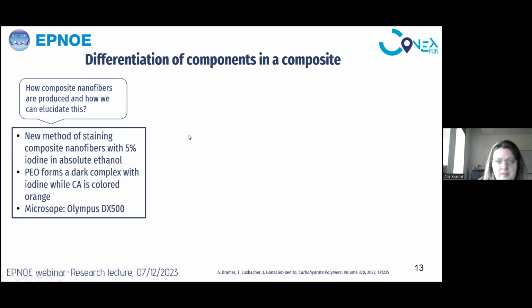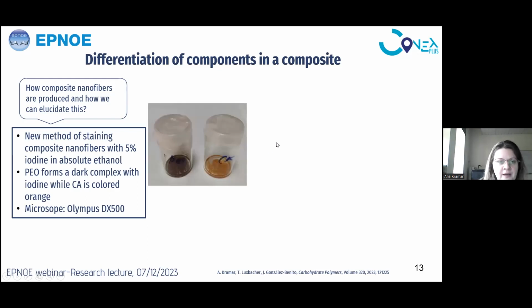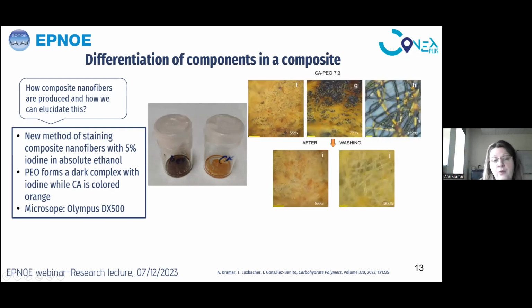We proposed a new method of staining composite nanofibers with 5% iodine in absolute ethanol. Why? Because polyethylene oxide forms a dark complex with iodine, while cellulose acetate remains orange after coloration with iodine. And we were looking at the fibers before and after washing using an optical microscope. And what we saw were really interesting findings. Here you can see in image H that we saw a dark coating around orange stained parts of our nanofibers. Here, after washing, we don't have this dark coating anymore.